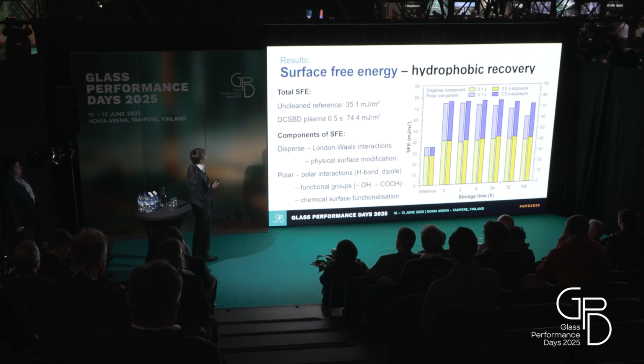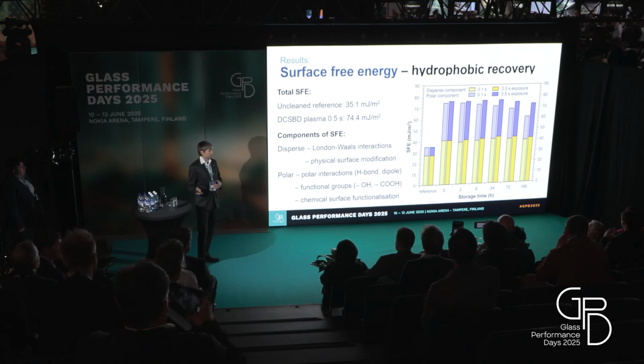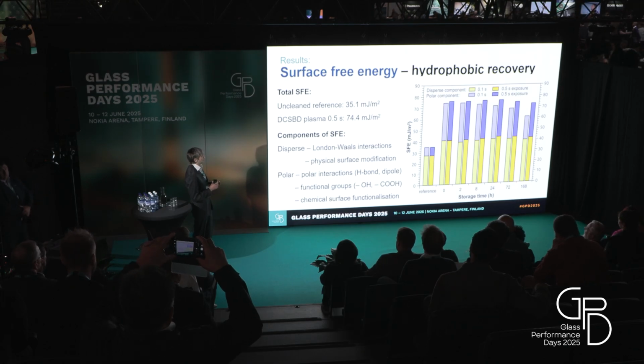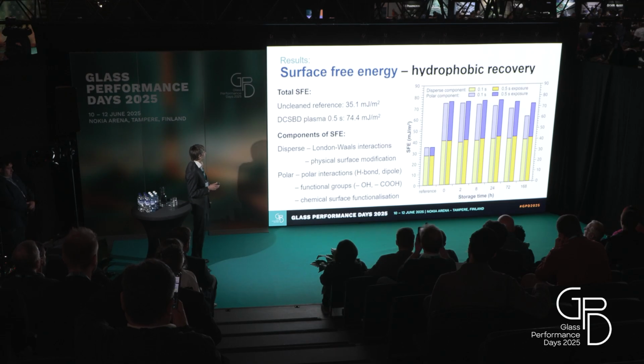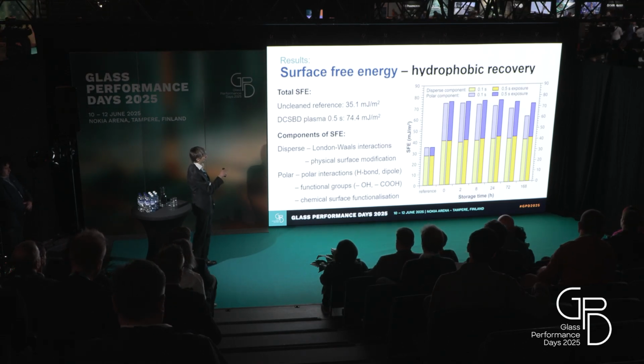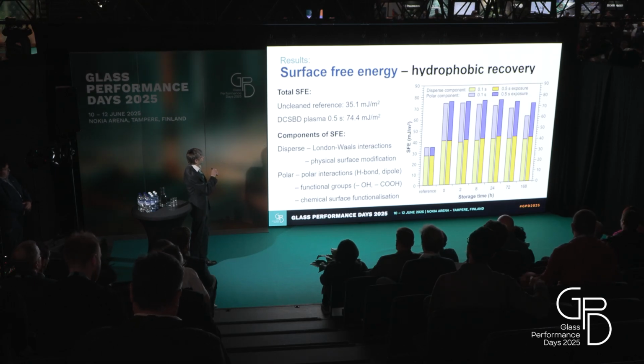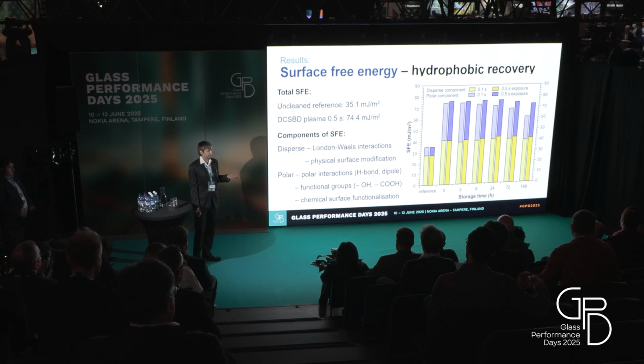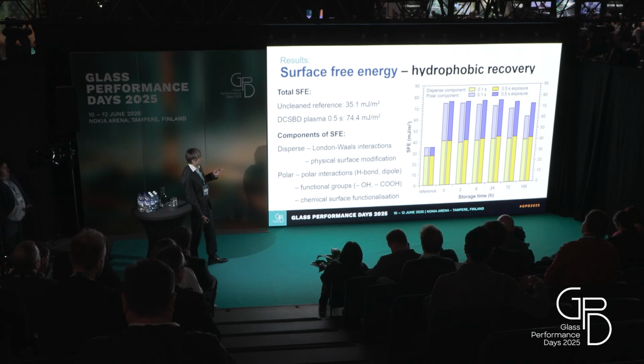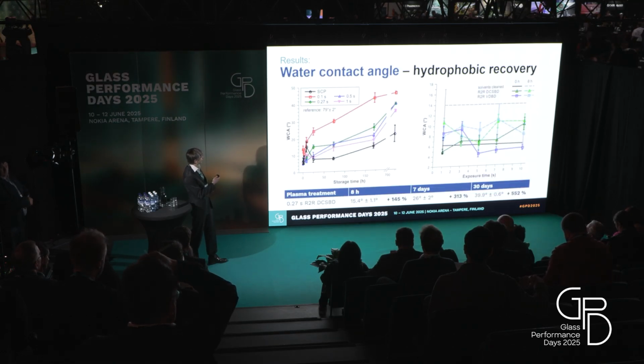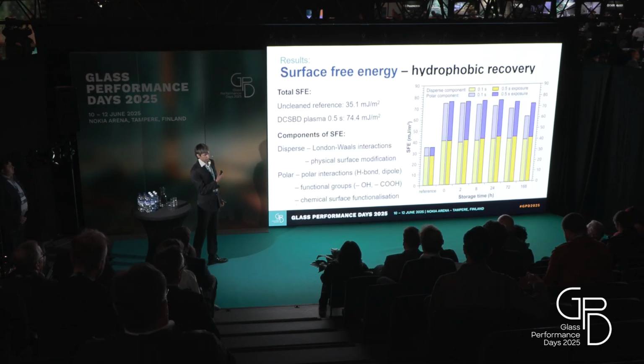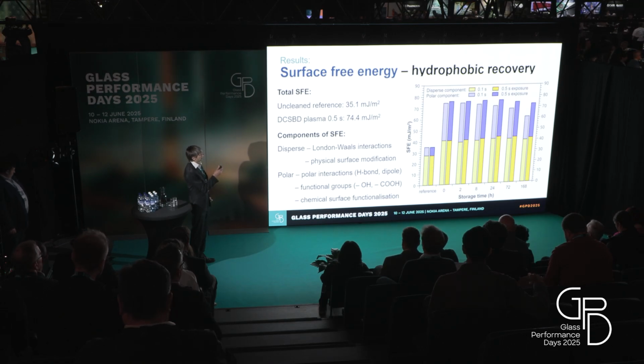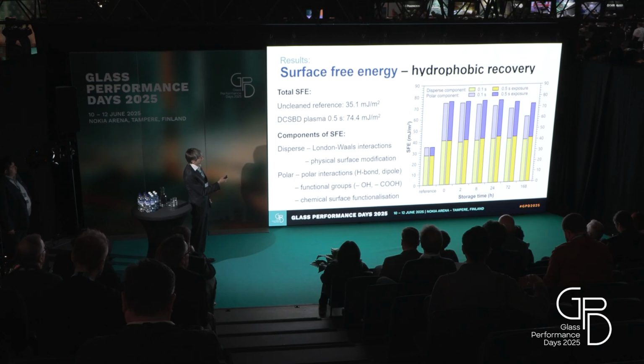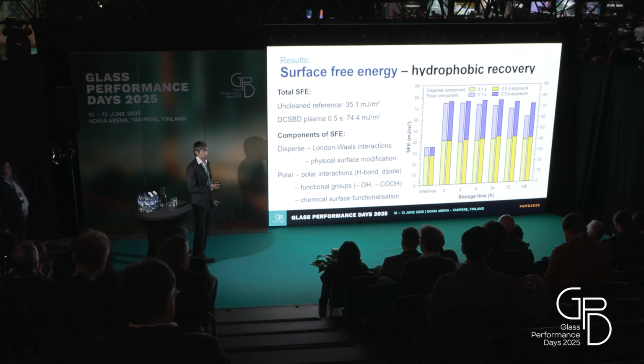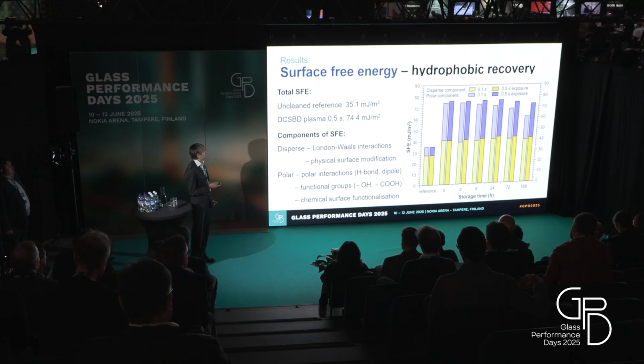So let's first see the comparison with water drops and drops of diiodomethane, which allows us to evaluate components of surface free energy. And one of these components is the disperse one, which is more by physical surface modification. It's the yellow one in the graph, and the blue one, the polar, is the component which belongs to functional groups, which we expect that we generate in plasma. And we can see that 0.1 second, which has much faster aging, the red line in the left graph, compared to the 0.5 second, which aged not so fast, then it can be seen that only the polar component changed. After 7 days, it was reduced to close to half. So the instability of the coating belongs to the decrease of this polar component.